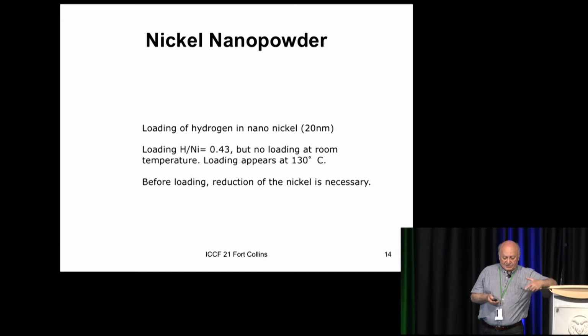And after this treatment, I introduce hydrogen at room temperature. It doesn't go inside. So if I start increasing the temperature, then you see immediately the pressure drop. I measure the loading by the pressure drop. It's quite easy. Then I increase the pressure again, and the pressure drops even faster. It's amazing. It could go up to 0.43 loading at about 130 degrees C. So this is very important for future applications of nickel nanopowder.